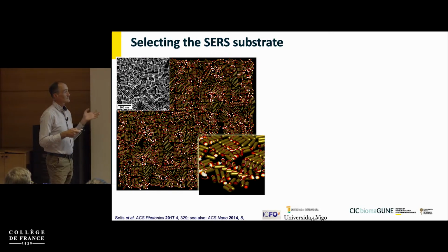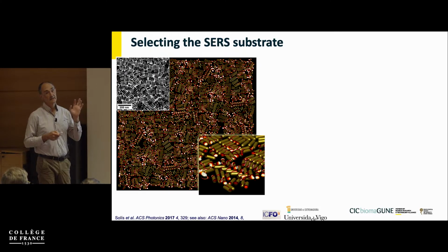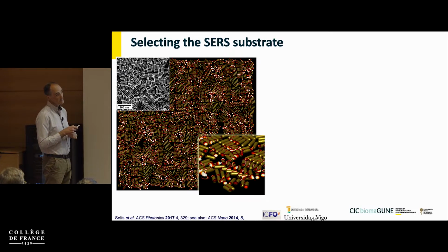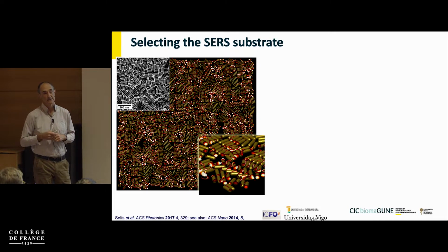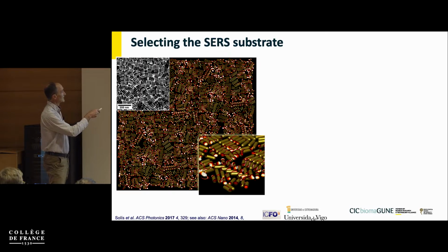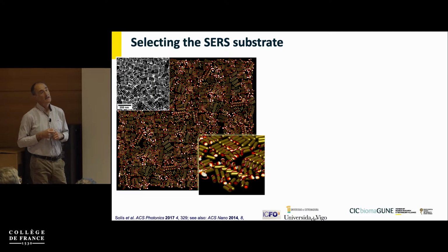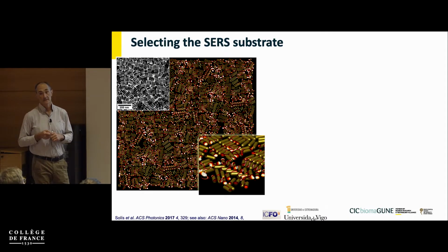And so in fact, when you run a surface enhanced Raman experiment, you obtain the signal mainly from the molecules that are located at those spots. The rest of the surface is almost useless, okay? And in this particular case, you see all these areas where there is sufficient distance between the nanoparticles are basically silent. They do not provide anything to the signal that you record.